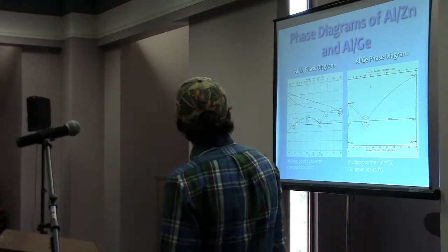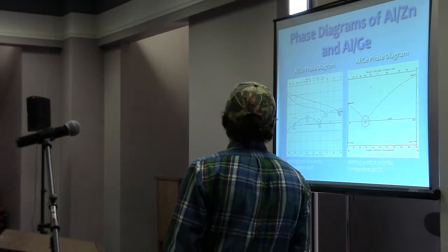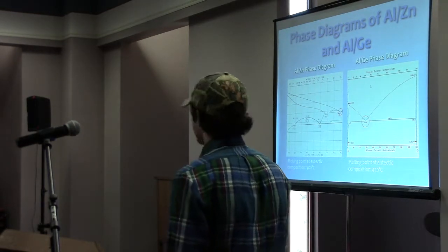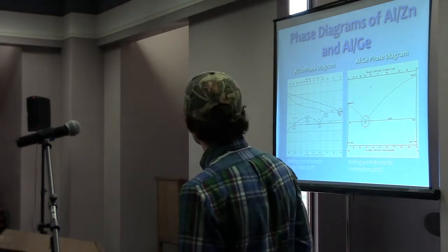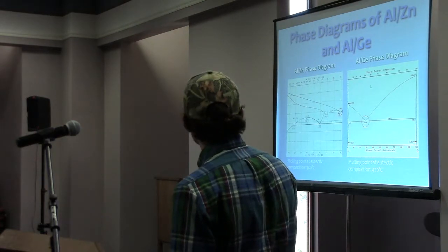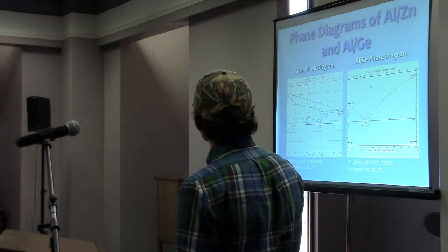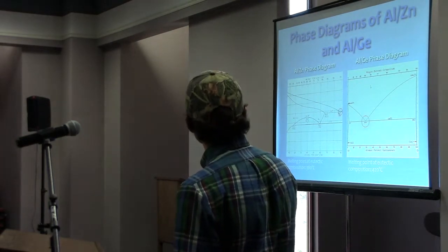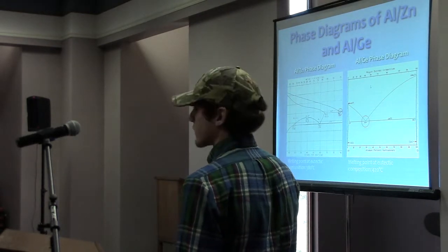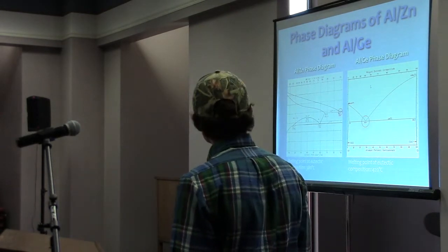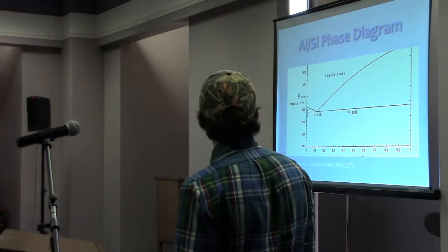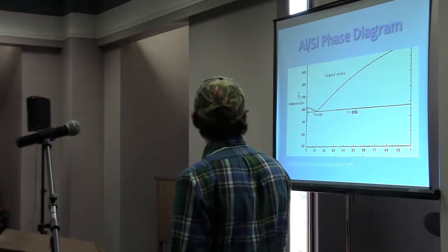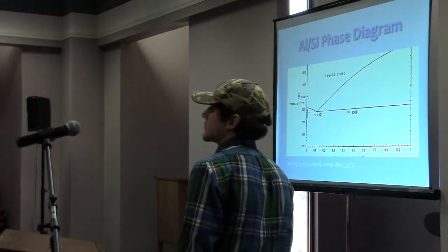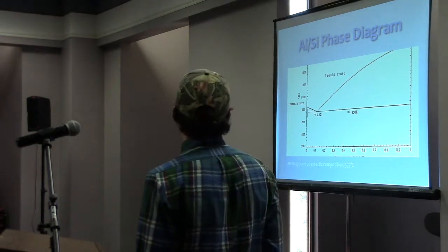This is our aluminum-zinc phase diagram on the left, showing the eutectic point where we're studying, which is the lowest melting point where it goes straight from a solid to a liquid phase. And for aluminum-zinc, that was about 380 degrees Celsius, and for aluminum-germanium, it happened at about 420 degrees Celsius. And that's just the aluminum-silicon phase diagram. And the same thing, it's melting at a much higher temperature, about 577 degrees Celsius.